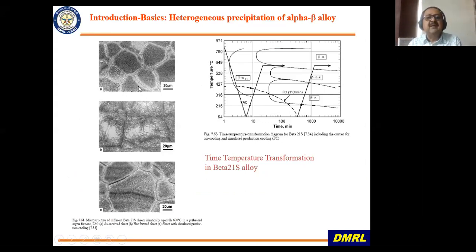So that is why while processing beta alloys, you have to be careful, and there are strategies for processing all the titanium alloys as well as beta alloys, so that you don't get much precipitation of alpha around the grain boundaries. But that is a common thing in beta alloys, and you need to be careful.